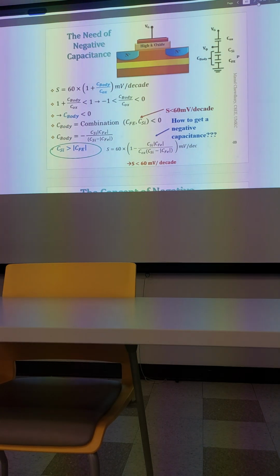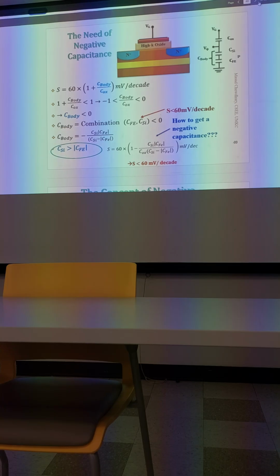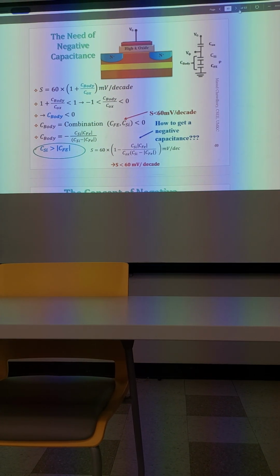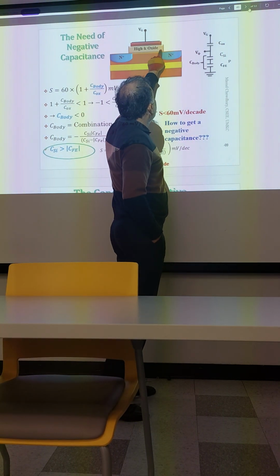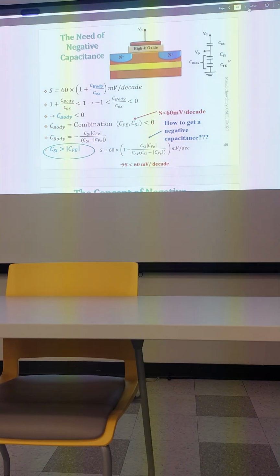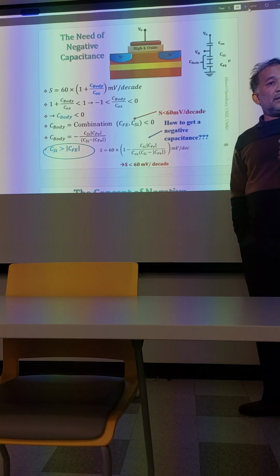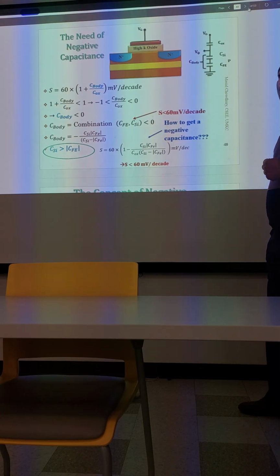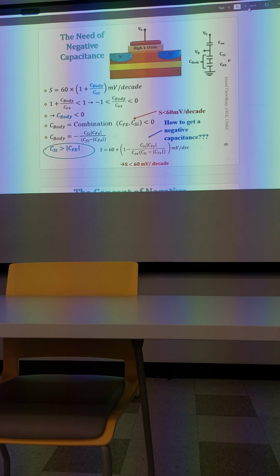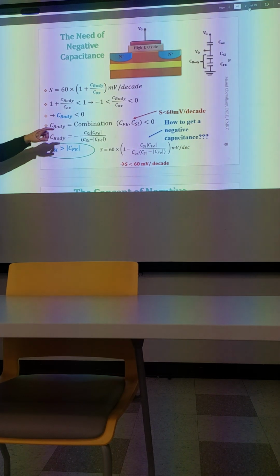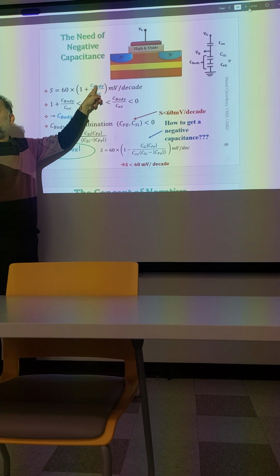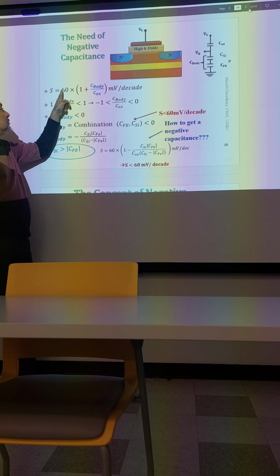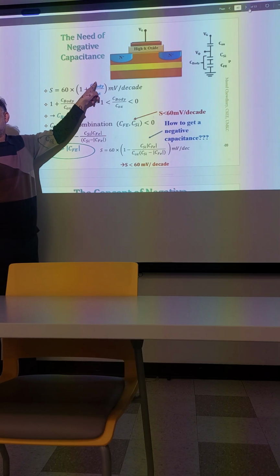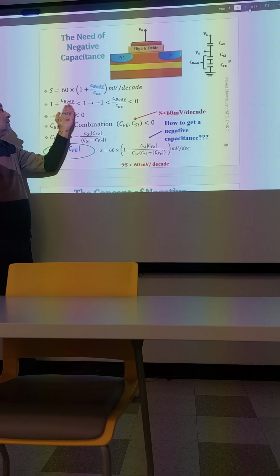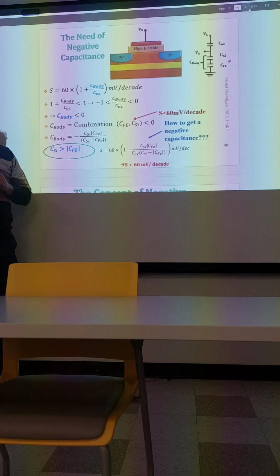So I mentioned that Sayeef Salahuddin and his advisor Supriyo Datta introduced this concept of introducing negative capacitance inside the MOSFET device structure. They introduced the idea by introducing an insulation layer here in the gate, replacing the original insulator silicon dioxide with a ferroelectric insulator. That ferroelectric insulator has the ability to display negative capacitance under certain operating conditions. With that, if one of them, body or oxide capacitance, becomes negative, this fraction becomes negative. So subthreshold swing will be 60 multiplied by a fraction smaller than 1. Because then it becomes negative, we will get less than 1 as the factor. So this will be smaller than 60 millivolt per decade.